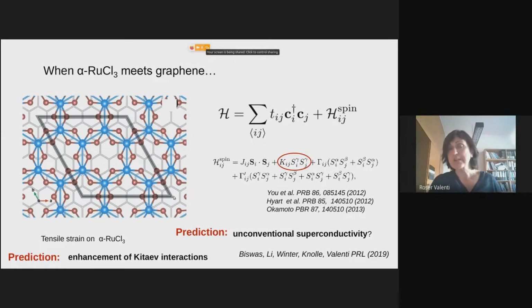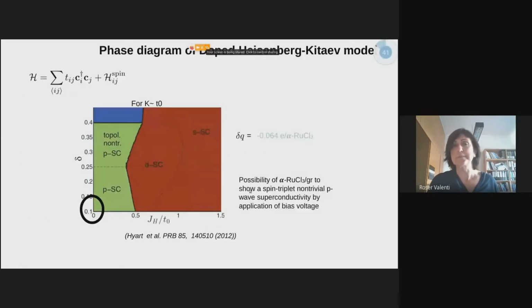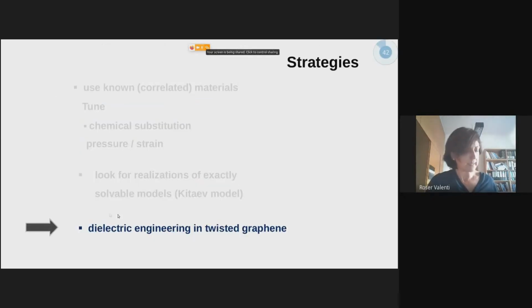Moreover, because of this charge transfer, there is charge coming to the system. And what we predict is that if one now would apply a bias voltage, you could even find a P-wave type of superconductivity in this system. So you see, by making use of these 2D systems and starting to put them on top of the other in different ways, one can obtain emergent phases that were not possible in the single materials. And since I think I am done with my time.